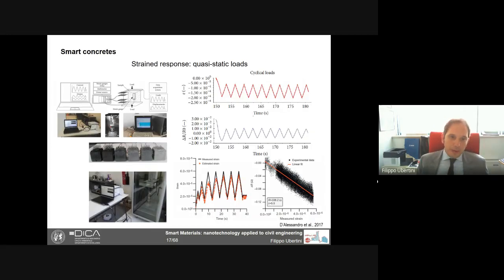So we know how to fabricate these materials. We know how to measure. So let's see what happens if we apply a strain. Like, for example, here you see some test under compression on cubes of smart concrete. On top right, you see the applied strain in red. And in blue, you see the electrical response of the sensor. Let's call it a sensor. It's just a cube of concrete with 1% of multi-wall carbon nanotubes with respect to the weight of cement.